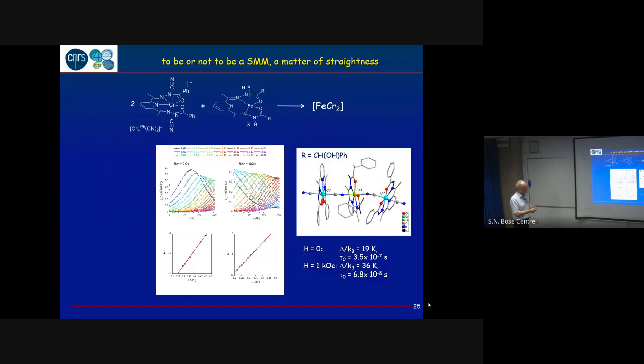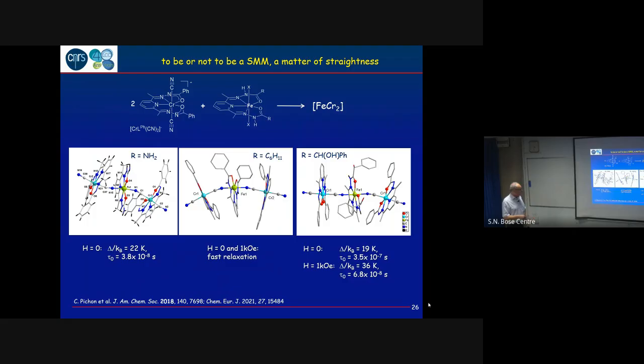So we have made different compounds, very similar. The difference between these, from a chemical viewpoint, is that we have changed the R group that is here. So in the example I discussed before, this is the R group. Here we have a cyclohexyl, and here we have an NH2. And in all cases, we have the trinuclear species, but when you look at the magnetic behavior, well, this is the compound from before, a single molecule magnet, and this one, very fast relaxation. And the third one has a behavior that is in between. But there is no difference in the anisotropy, there is no difference in the composition of the compound. So it was a little bit surprising to us to see.